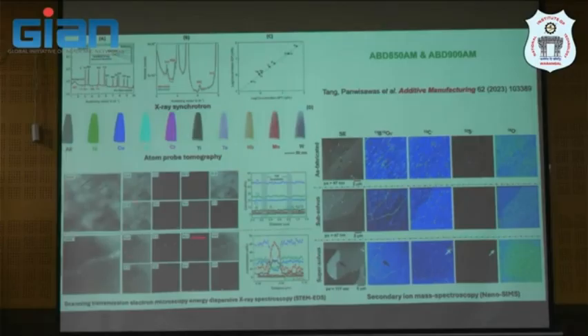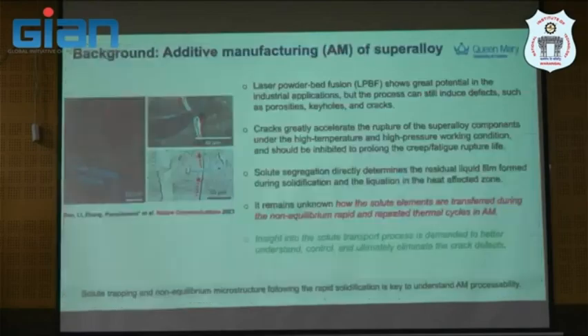And atom probe also shows some segregation, but it's not actually heavy segregation. If we do post treatment at different subsolvus or supersolvus temperatures, you can actually segregate out or homogenize some structure. And then this is quite a solid solution. If you see the profile here, yeah, there's something across the boundary a little bit. But this is what we got, and then we know that, okay, this is different from existing alloy.